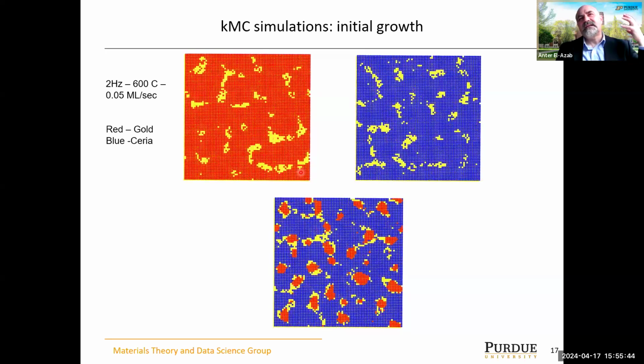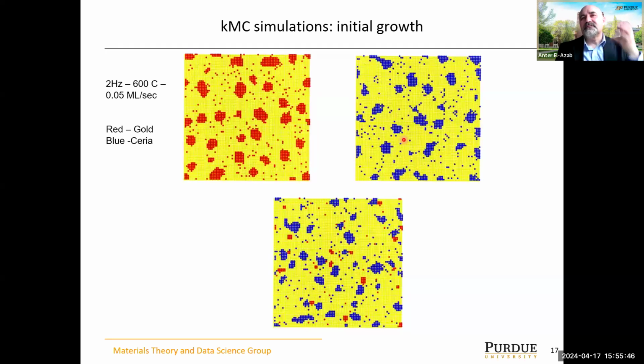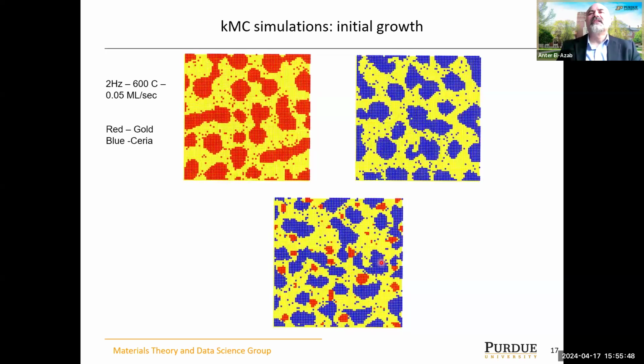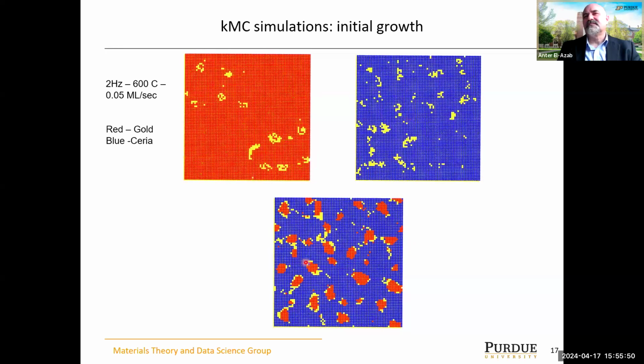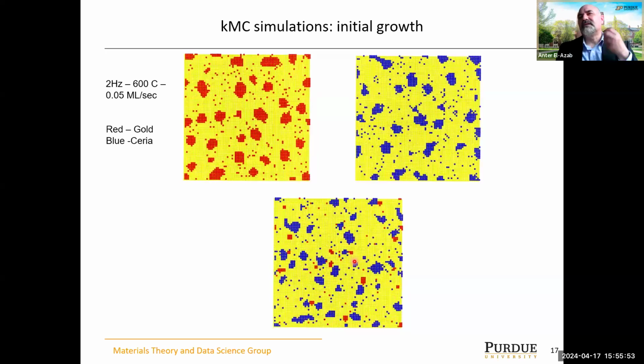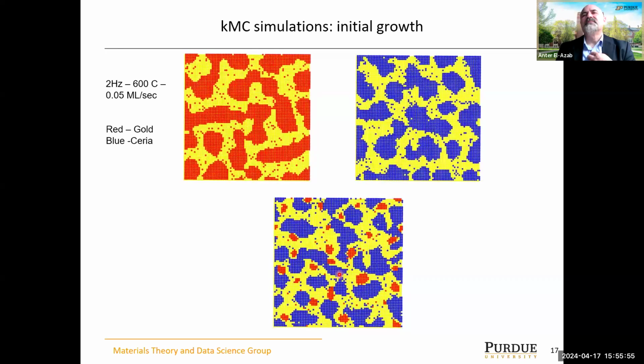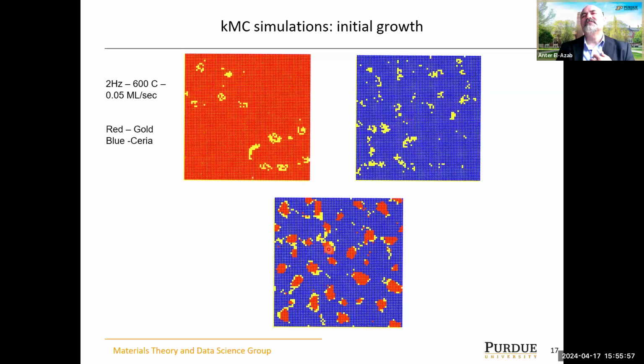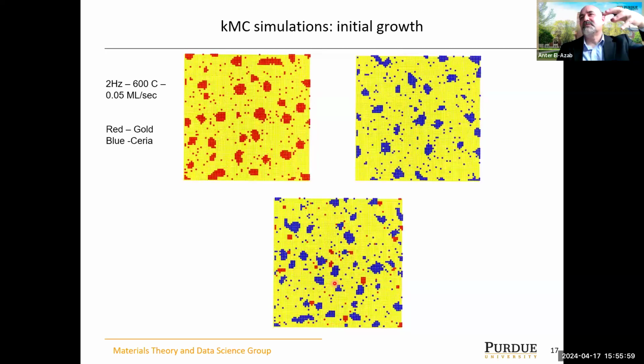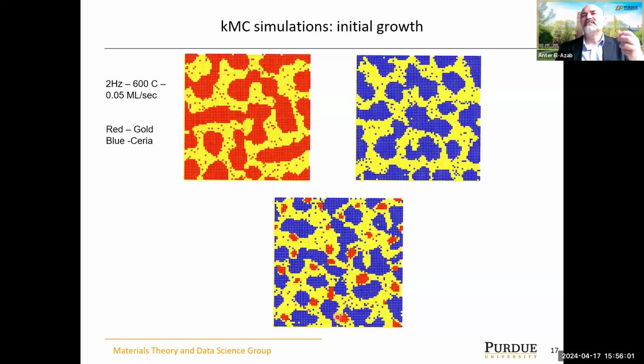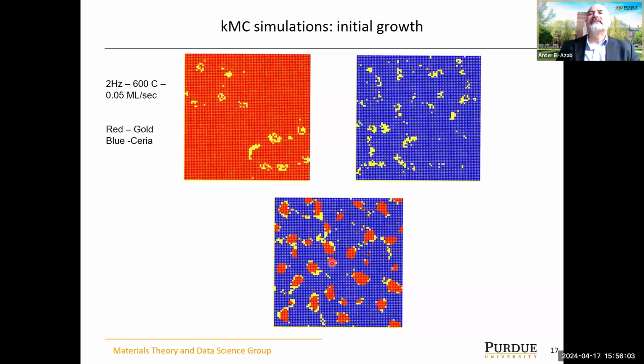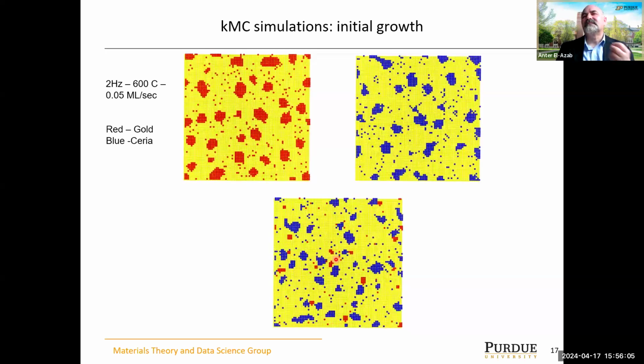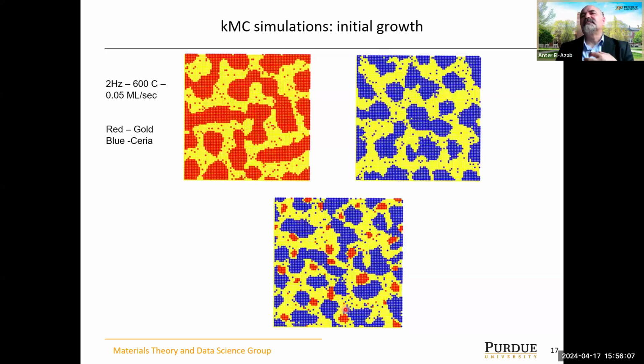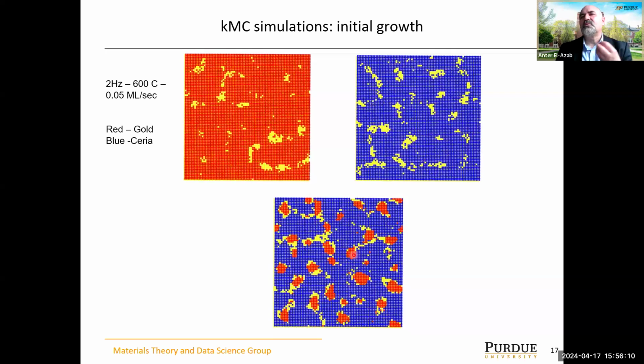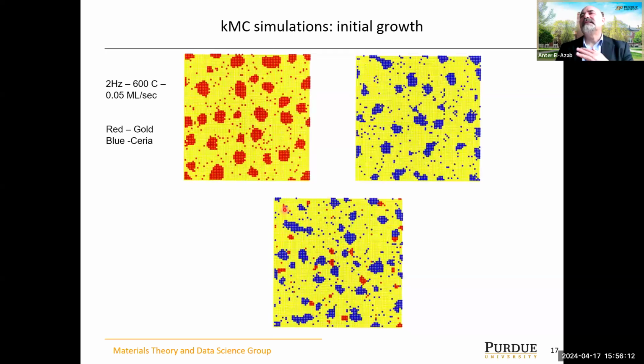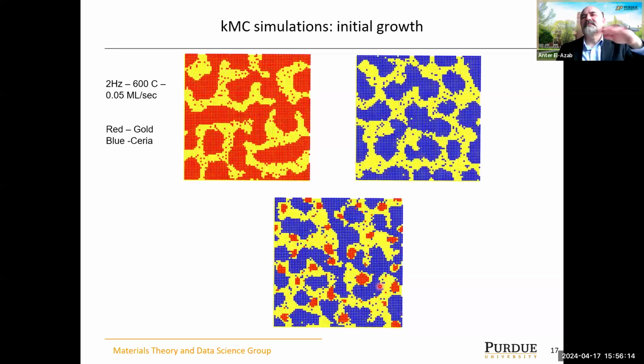In our case, we're actually depositing the gold and the ceria together, and you end up with something like at the bottom here. You have them deposited by a certain mass ratio. So at the end, the collection of the red and the blue masses is what you have added to the system. But the simulations tell you about how the red is distributed within the blue phase here. The red is a gold phase. This is just one layer, the very initial layer in the system.